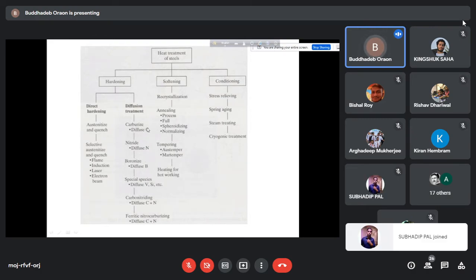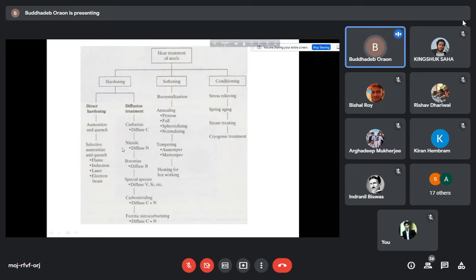Then you have the diffusion treatment. We have studied diffusion in detail. So we can diffuse some required atoms or elements within the parent material, and we can increase the hardness. One is called carburizing, basically diffusing the carbon atom. Then we have nitriding, diffusing nitrogen atom. We have boronizing, when we diffuse boron atom. Like that, we have different diffusing elements, it can be vanadium also, silicon, then a combination of carbon and nitrogen, which is called carbonitriding.